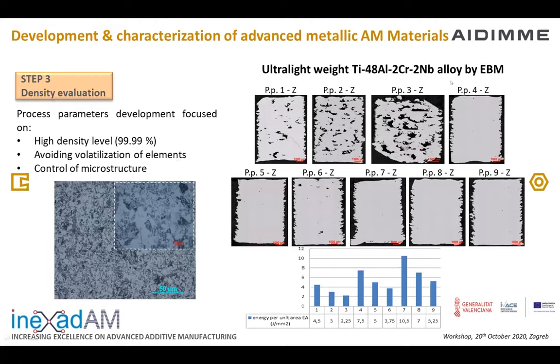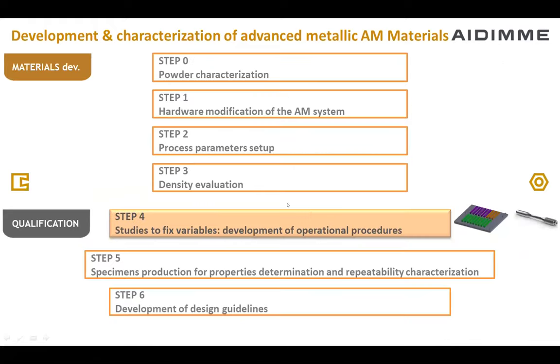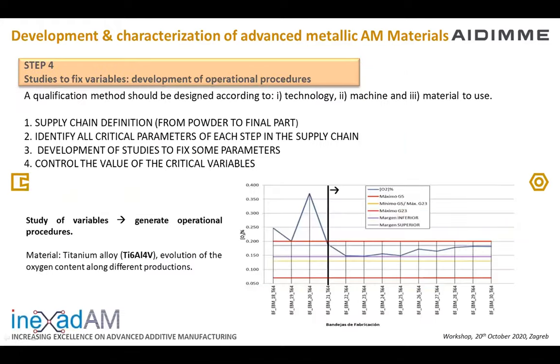For example, here we have an example of a titanium aluminum alloy. So in this case, we control at the same time that we wanted to reach a high density level, and you can see here the evolution of the density level. We perform the controlling of the microstructure and also the analysis of the chemical composition in order to not volatilize the aluminum in this case. So at this point, now we will see the following step related to the qualification process for bigger parts.